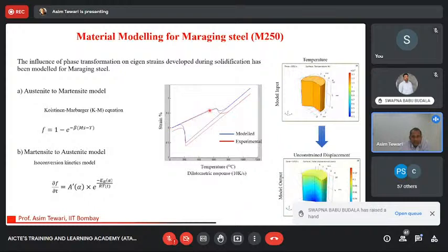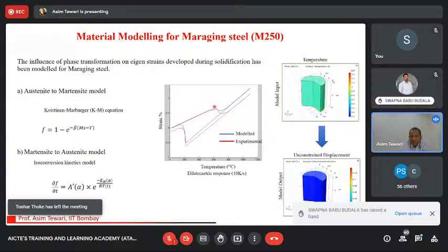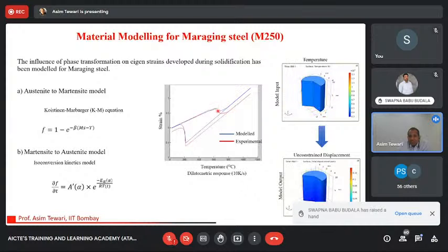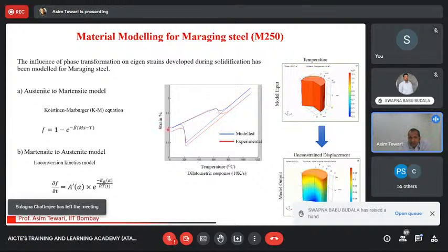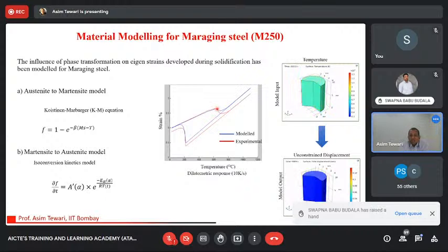Because this is martensite in the beginning, and the martensite is expanding with increase in temperature. The moment you reach a temperature at which martensite transforms back to austenite, which is given by this expression, it becomes austenite. And austenite is an FCC material which has a lower cell volume, higher density. Martensite is body-centered tetragonal, which has more volume per cell and thus less density. So it's more voluminous. So the moment it forms austenite, it goes through a reduction in volume, and thus the strains fall. So what you need to realize is there's a thermal expansion which is causing these strains to grow, but there's a phase transformation which causes this strain to fall.